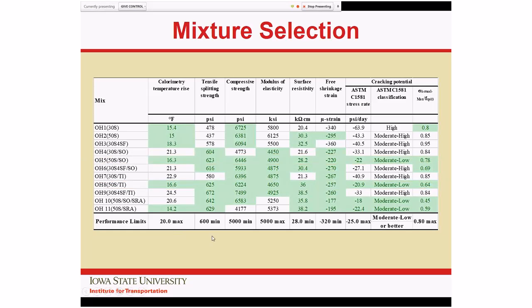On the splitting tensile, most specifications run with a 600 or 650 psi minimum. We chose the 600. Compressive strength, we went to the 5,000 psi minimum. Modulus of elasticity, we went to the 5,000 ksi maximum. For resistivity, we chose that number I referred to, 28 kiloohm centimeters, as a minimum. Free shrinkage, we went to 300, which is the number I've seen in several specifications.